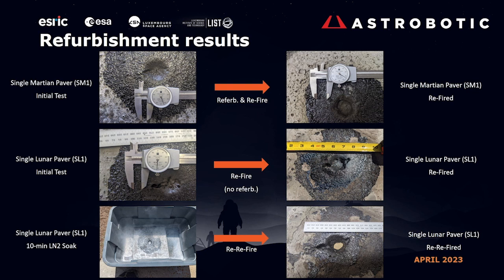And at that point, we did burn through the pad after a third firing, but we were really excited to see that there was no thermal shock in the pad. We didn't crack it, which we really kind of thought we would. So this spoke really well to the resiliency of this amorphous matrix that we're using to bind the regolith.